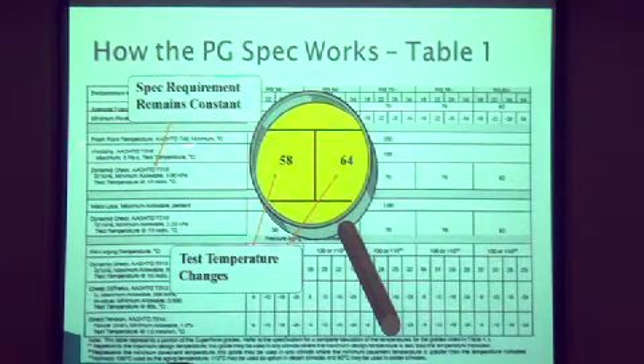And this section here deals with properties on the unaged binder, then you have properties on the RTFOT binder, and then you have properties on the PAV aged binder. So you have different properties to control the parts of the specification that deal with rutting, parts of the specification that deal with fatigue, and also with low temperature cracking. And then you have flash point included in the specification. There's a safety aspect.